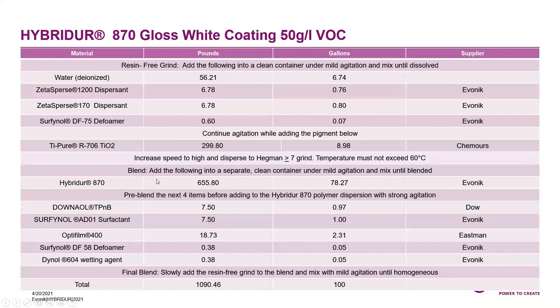And then blend, add the following into a separate clean container under mild agitation. So we blend the coalescing solvent, in this case Dowanol TPnB, Surfynol AD01 surfactant, another coalescing agent called Optifilm 400 from Eastman, another defoamer, and a wetting agent. So a surfactant, a defoamer, a wetting agent, followed by the two coalescing agents. These are premixed and they are added to the Hybridur 870 polymer, and the pigment dispersion is directly added to that mixture with agitation. So it's fairly easy to formulate.